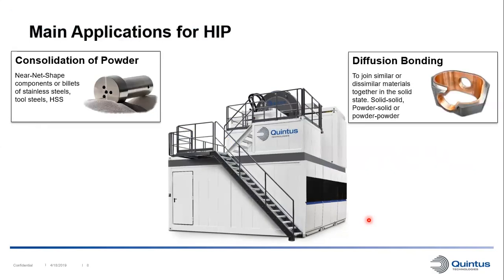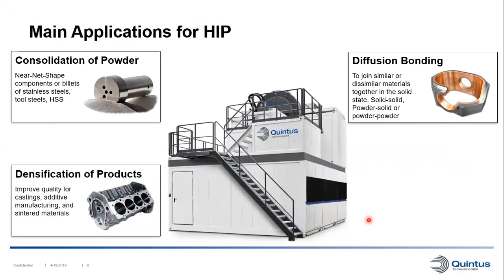Diffusion bonding is another application where similar or dissimilar materials can be bonded together in the solid state. So there's no melting in this process. And you can bond a solid to a solid, also clad a powder to a solid, and also do powder to powder compounds. The third main application for hipping is densification of products. This is commonly used for casting, additive manufactured materials, or sintered materials, any material that contains some kind of internal defects that can be eliminated. And this is the application that we will be focusing on today.